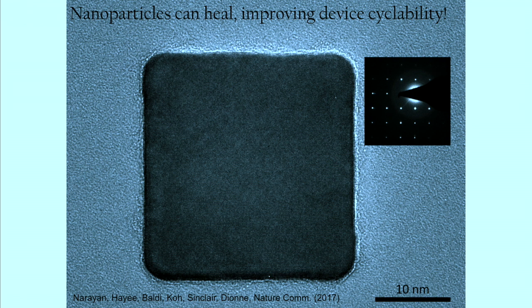So this only happens in a certain size regime of nanoparticles, but it shows that nanoparticles have this self-healing ability, which helped to explain the extended cyclability of these nanostructured devices or electrodes. But we can use this as a design principle to make even better energy storage materials or photocatalysts. Okay, so beyond just single crystalline nanoparticles, we can also look at a variety of other shapes. And regardless of the shape or the polycrystallinity of the nanoparticle, we always have loading from the corners, or these low coordination number sites. So how is it that we can potentially modify where reactions are occurring and make more of the catalyst area? So that's where illumination comes in.